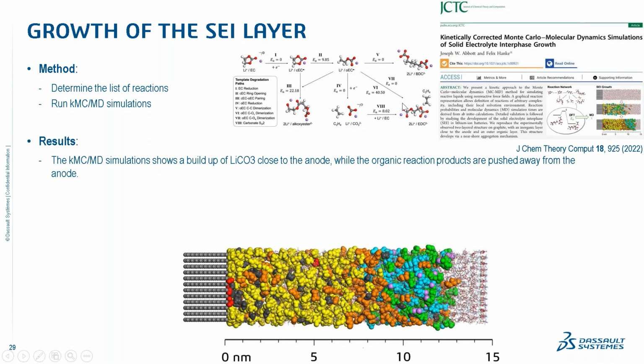Once we have that, we can perform molecular dynamics simulation where we also include kinetic reactivity steps. So that means we're running a short period of molecular dynamics. We are stopping and we are investigating if any chemical reaction might happen in a kinetic Monte Carlo sense. So we're calculating probability for chemical reactions. If there is a reaction happening, we are changing the state of those molecules involved, and then running another molecular dynamics to progress the time in the system. And in this way, we can propagate and simulate how the processes at the anode in the electrolyte are leading to the growth of the SEI layer.